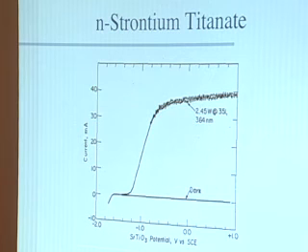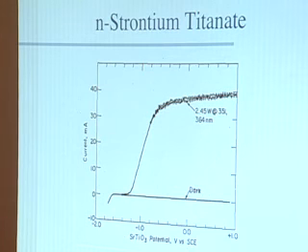And the reason this line is jiggling here is this electrochemical cell looks pretty much like a Coke can that you have shaken up, and you've got so much hydrogen and oxygen bubbling out of this solution that it's scattering the light everywhere, and that's what that jiggling is, the light shooting in all different directions. Okay. Very stable semiconductor, works at amazingly high intensities with a quantum yield for a charge transfer of 1, and the only problem is it requires UV light. It's a wonderful semiconductor, and it was my first publication out of the Wrighton group.